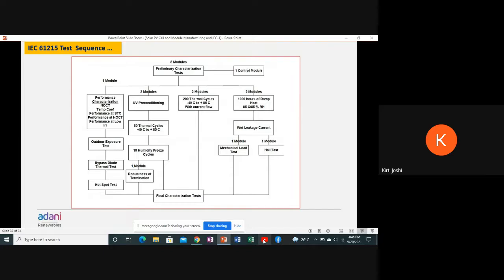One module is tested for performance characteristics, that is NOCT, temperature coefficient, at STC, and for low irradiance. These are the performance tests. Then the outdoor exposure test and bypass diode test. Another module is tested for UV preconditioning, then thermal cycling. The thermal cycling is also specified in the IEC, for temperature cycles from minus 40 degrees centigrade to 85 degrees centigrade. Then the humidity freeze cycle, where the module is placed in a chamber with the humidity and duration specified in the IEC, and the robustness of termination test.